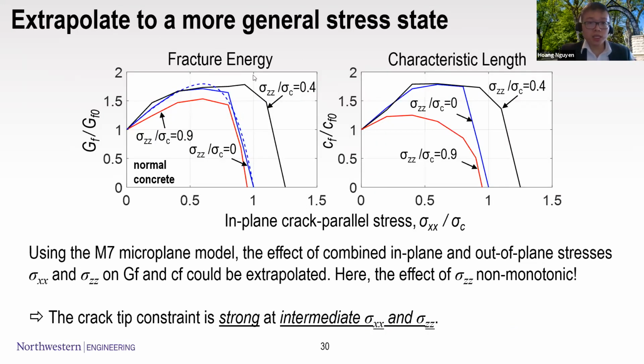So we see the effect of sigma xx, which is pronounced in the fracture energy of the material. So how about out-of-plane crack-parallel stress? Here we have done some prediction using the out-of-plane crack-parallel stress sigma zz, and we can also observe a non-monotonic trend when we apply sigma zz.